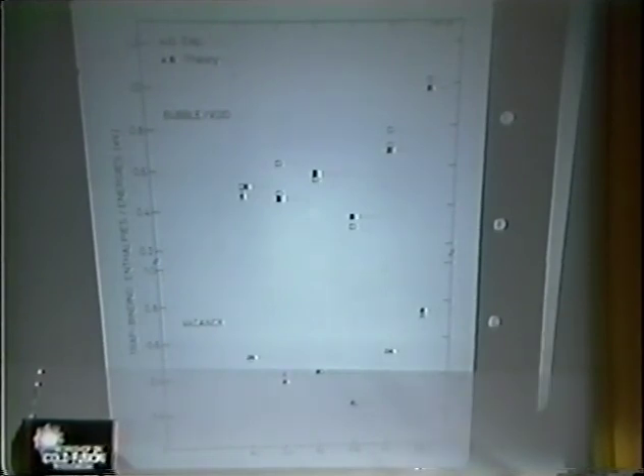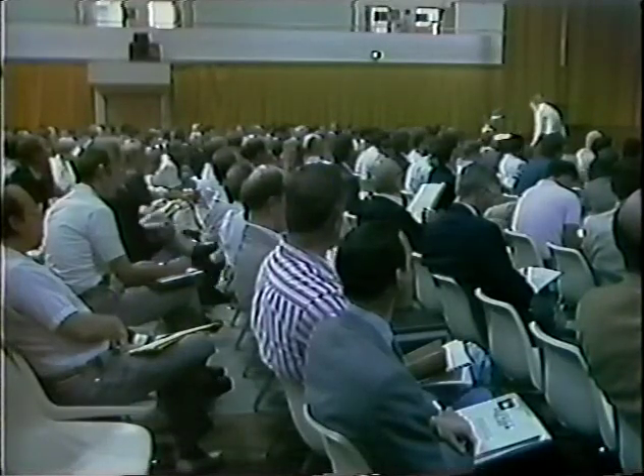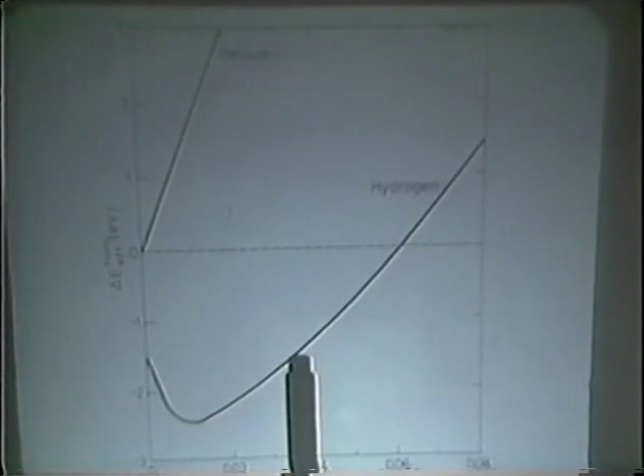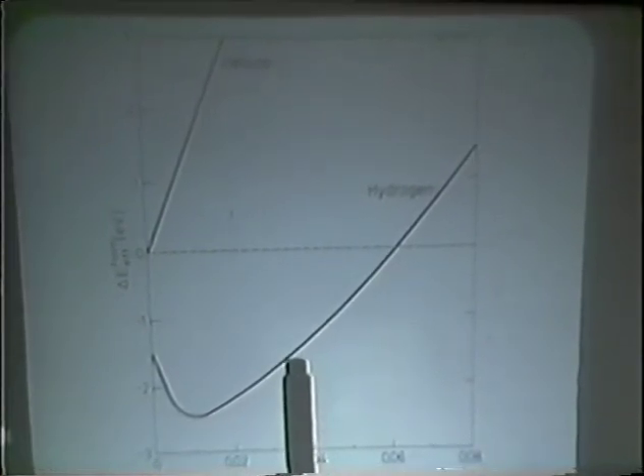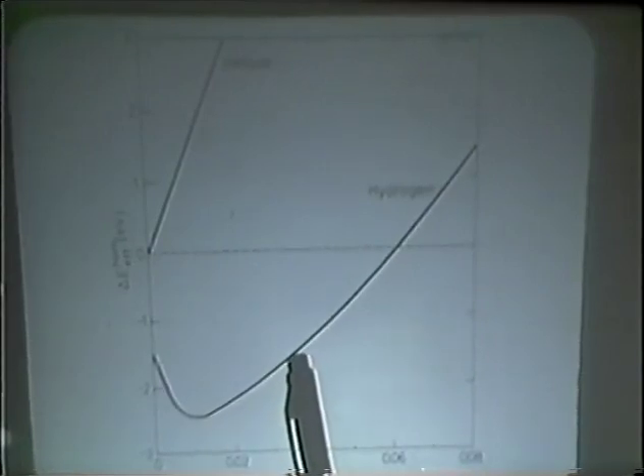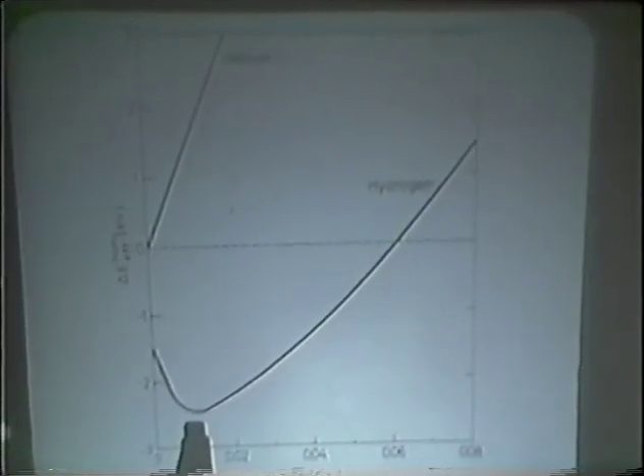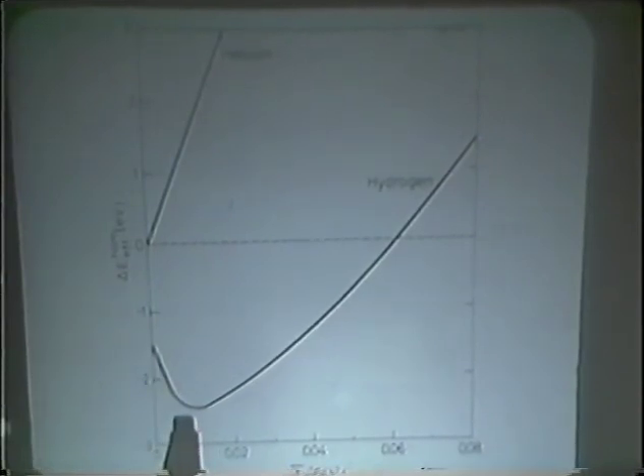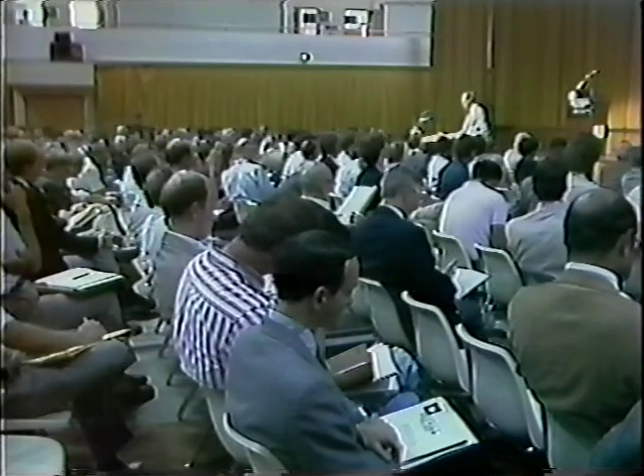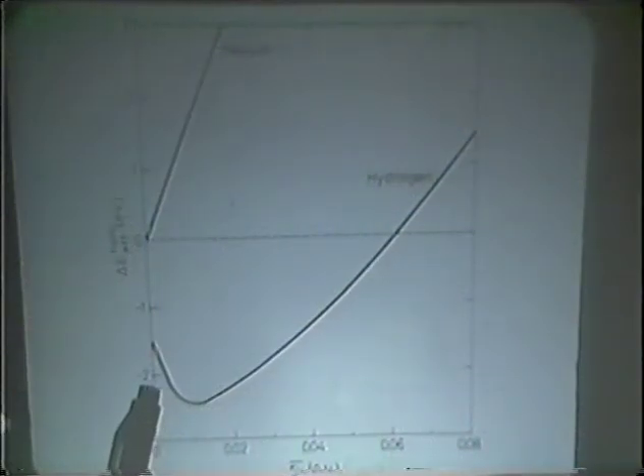How can one now understand this? That's again fairly simple to understand qualitatively from this curve here, because as I said, the trap strengths are measured relative to a solution site, and an interstitial solution site is lying on this linear part here. That means that any dilation of the lattice, a given trap with a given low interstitial electron density, would give a trap. You have the trap strength relative to a solution site up here, and then the trap strength, for example, for a vacancy, which has such a low interstitial electron density that we act down to the minimum here. Actually, the interstitial electron density in the vacancy is to the left of the minimum, implying that hydrogen will not sit at the vacancy, but rather be displaced somewhat away from the vacancy.